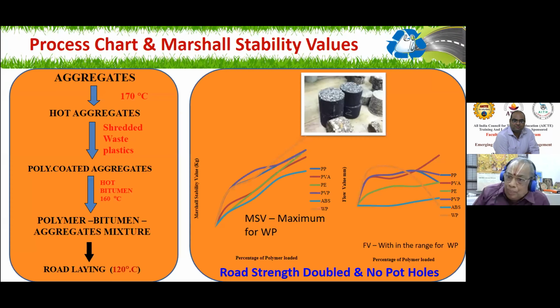And then the process. Very simple process. You take the aggregate, heat it to 170 degrees. Maximum temperature is only 170 degrees. And add the plastic over that hot aggregate, and it gets laminated. The stone gets laminated. Then over the laminated stone, just add bitumen, which is at 160 degrees. Mix it together. 30 seconds extra, you lay the road. That is the only thing.